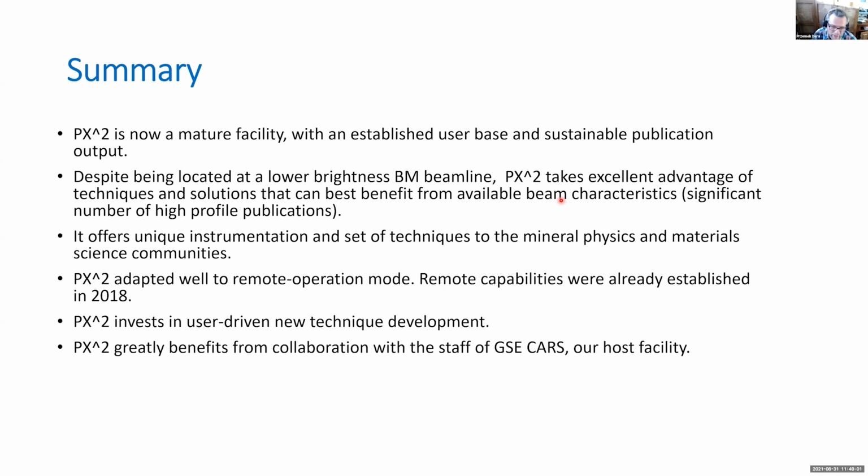Yes, so that's one of the bigger challenges. When you start heating samples, there's always a thermal gradient. When the samples go through a transition, different fragments of a crystal might go through a transition at different times, so it leads to a crystal breaking up into pieces. So when you perform these high temperature experiments that go across a phase transition, you usually end up with multi-grain